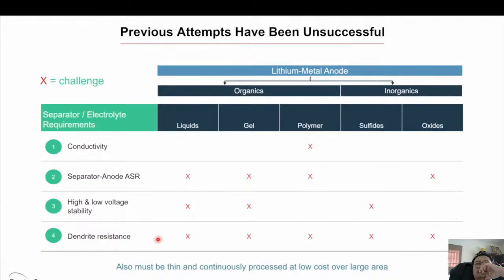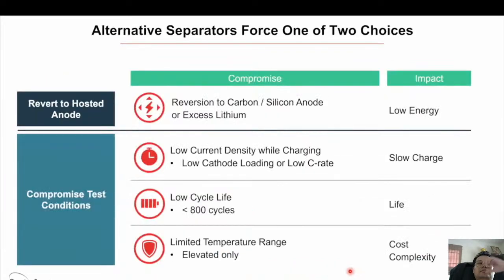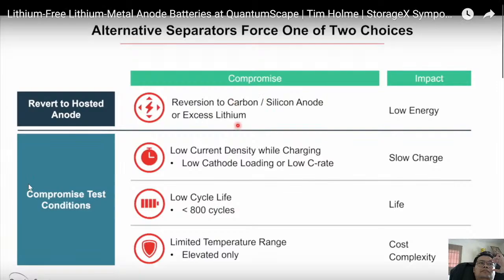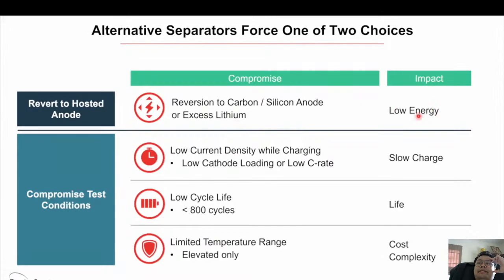Then finally, the separator has to be made thin, comparable to today's polymer separators, and processed continuously, not in batch modes or high vacuum processing, to enable low cost over large areas. So it's really a difficult challenge. And if you're not able to meet that challenge, there are a couple of fallback positions or compromises, either to revert to a hosted anode and use carbon or a carbon silicon anode again, or use excess lithium, at which point you're really diluting the advantage that a solid state battery can have relative to lithium ion in terms of energy density and cost.